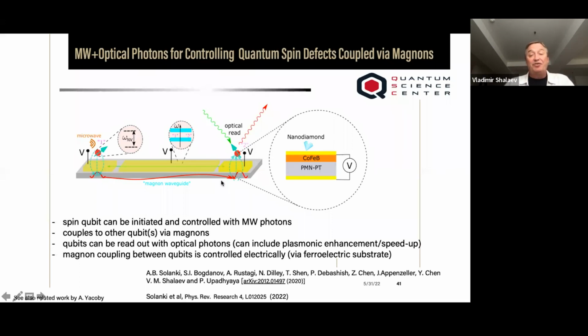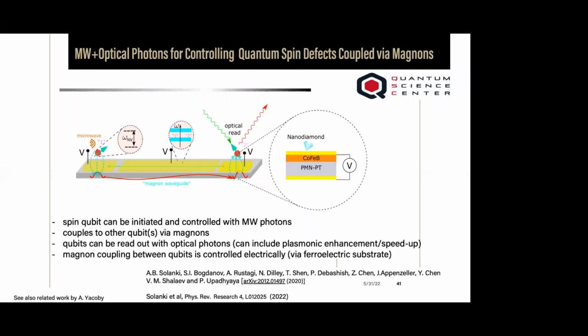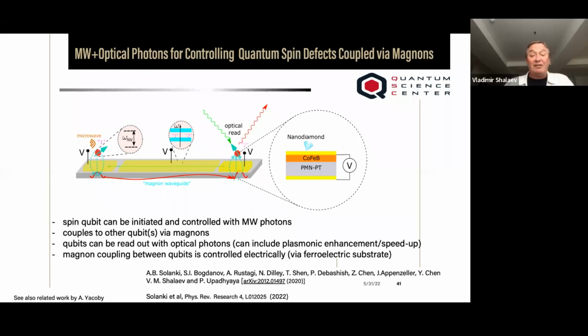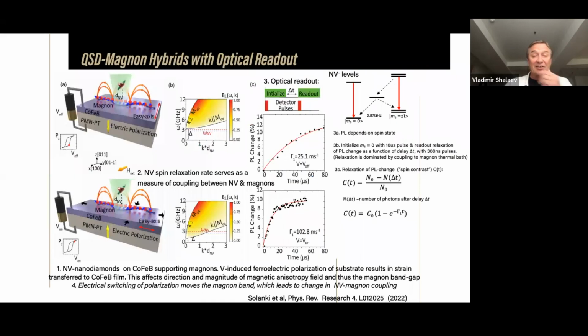If you place them on top of a magnetic film, which supports magnons, the different spins could couple, different qubits related to these spins could couple via magnons. And qubits could be read out with optical photons that could include this plasmonic enhancement and speedup, which I was talking about. And most importantly, this magnon coupling between qubits could be controlled electrically if you place them on a ferroelectric substrate. And that's what we recently demonstrated.